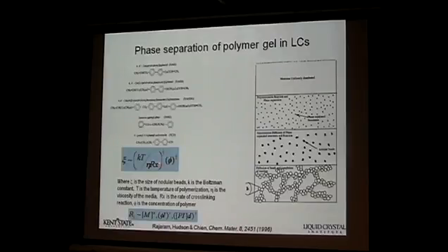So you form this. This is the reason that we want to learn this a little bit: using a small amount of polymer to modify these ferroelectric liquid crystals. Originally, Ivan showed yesterday that the molecules respond to applied fields. It rotates the dipoles in the direction of motion of the cone angles, right? If you have a small amount of polymer, you can suppress the cone rotation back and forth like this. Instead of rotating through a cone, it stays in the plane, more like the electroclinic effect, right?